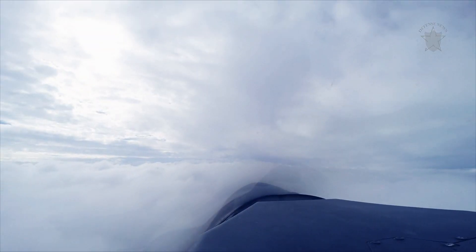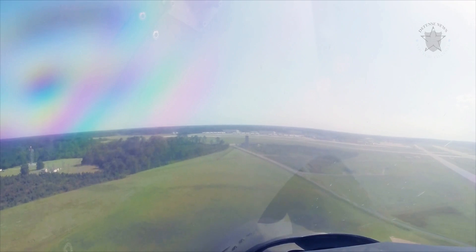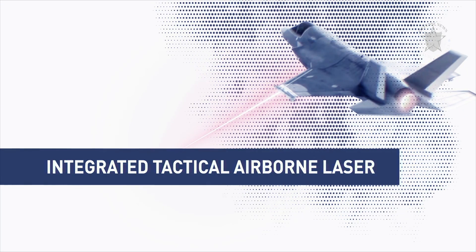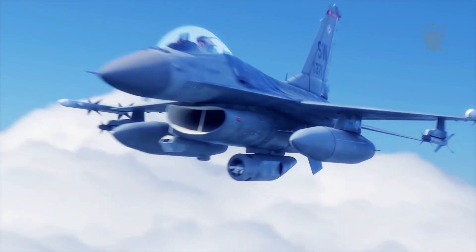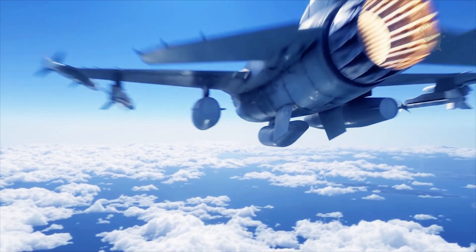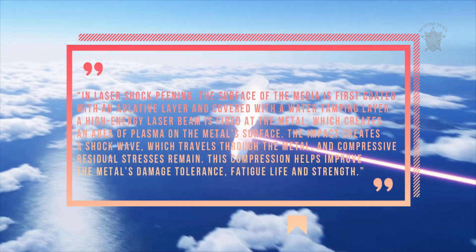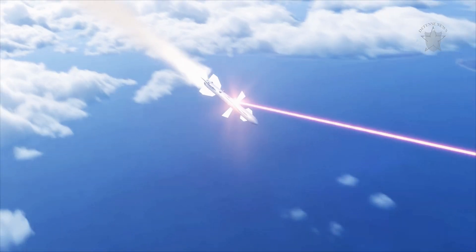A Navy report describes laser shock peening as a unique process producing a uniform result across the surface treated. According to a news report published on Navy.mil, in laser shock peening, the surface of the metal is first coated with an ablative layer and covered with a water-tamping layer. A high-energy laser beam is fired at the metal, which creates an area of plasma on the metal's surface. The impact creates a shock wave which travels through the metal, and compressive residual stresses remain. This compression helps improve the metal's damage tolerance, fatigue life, and strength.